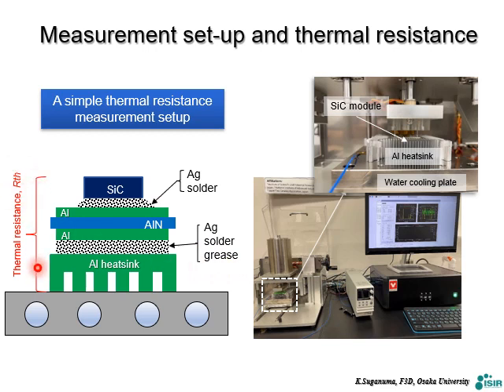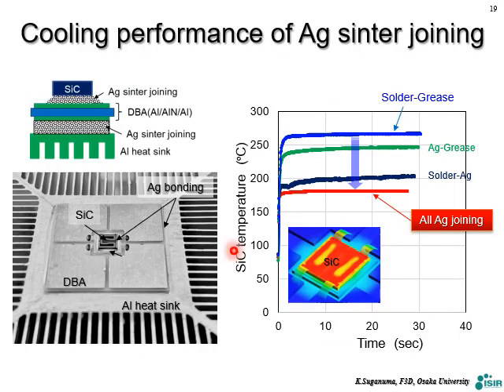And we measure the total thermal resistance by using this setup. And the result is very simple. So we changed the interface materials, and this is the actual structure. As you see, the aluminum heat sink usually has a very complex shape like this, so we cannot apply high pressure to make this assembly. So we don't apply high pressure actually. And the result is shown here.